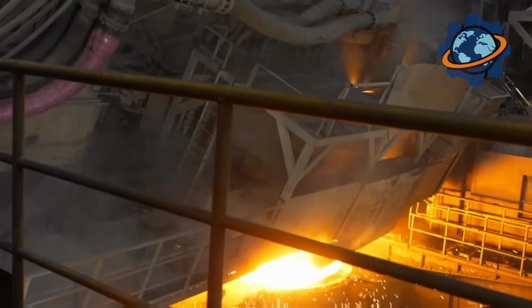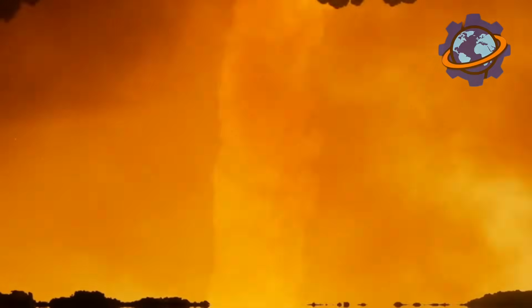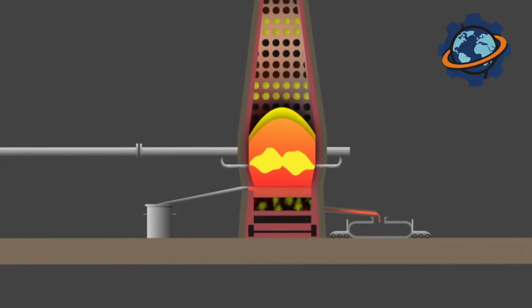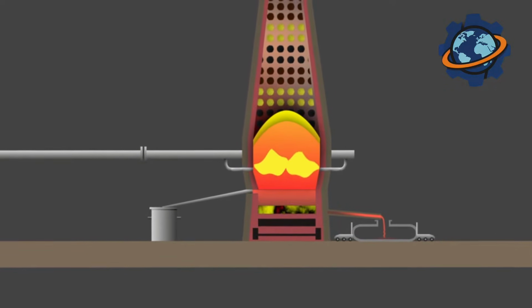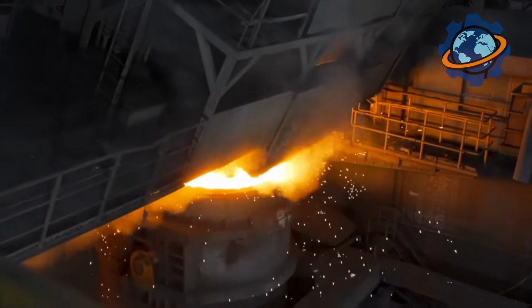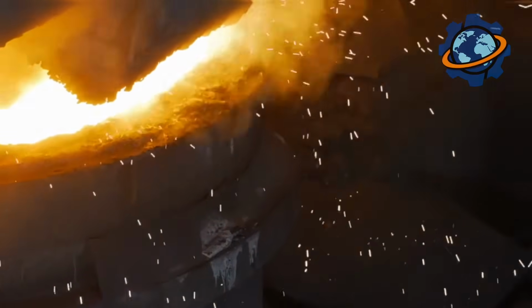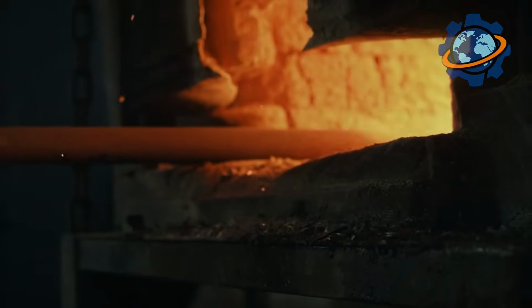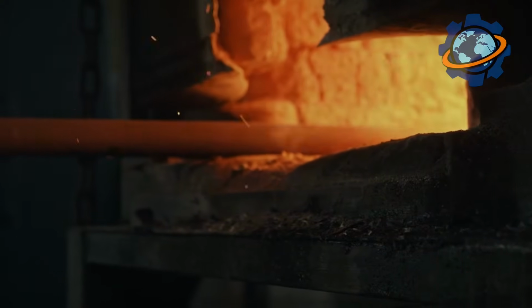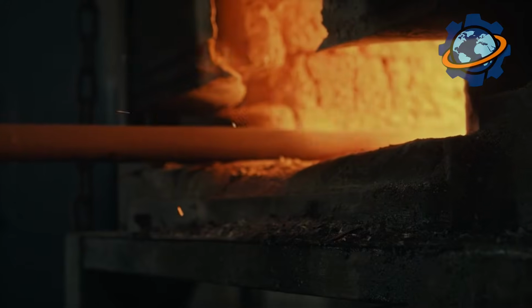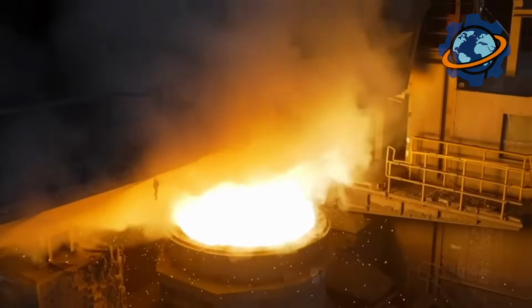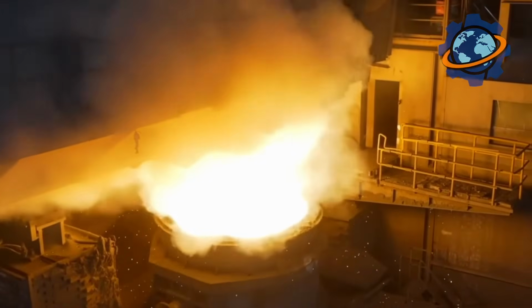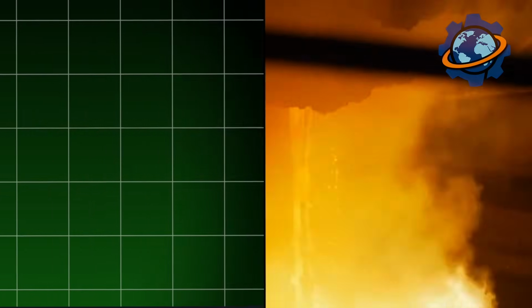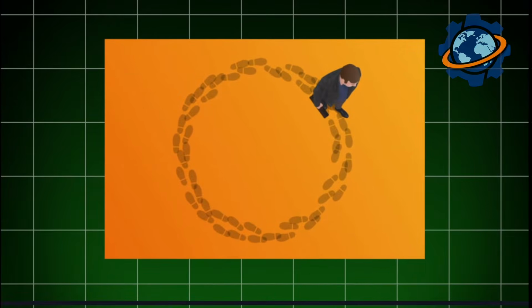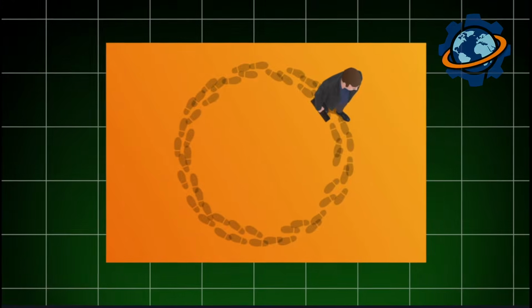A blast furnace is an amazing operation that produces more than just pig iron. The byproducts are just as important. The blast furnace slag, which we've already mentioned, becomes a valuable raw material for making cement, building blocks, and road aggregate after it's cooled and crushed. The blast furnace gas that comes out of the furnace isn't just released into the atmosphere. It's cleaned of dust and used as fuel to heat the very same air that's blasted back into the furnace. It's a closed-loop system that makes the process more economical.